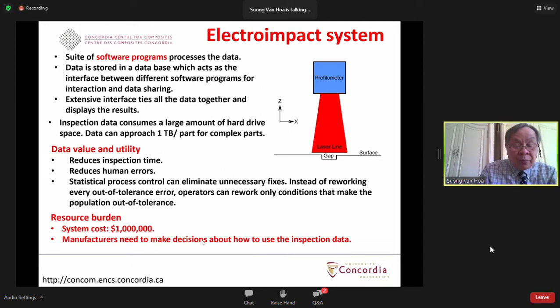However, this machine is not cheap. It costs more than $1 million. Besides that, the manufacturer also needs to make decisions about what to do with the inspection data. After you have seen the data, you have to decide what to do with it. If the defect is not severe, you say okay, I can live with that, I can move on. If the defect is significant, you have to repair it. And if it is too critical, you may have to reject the part.